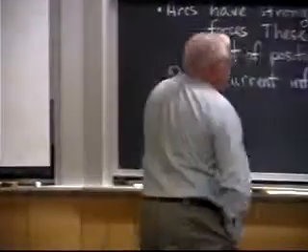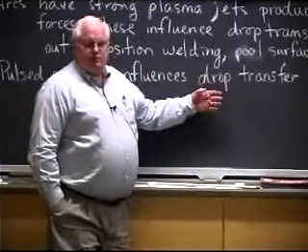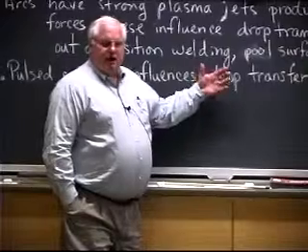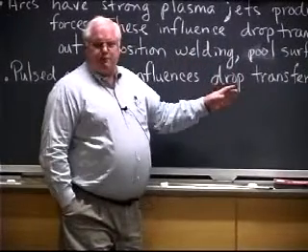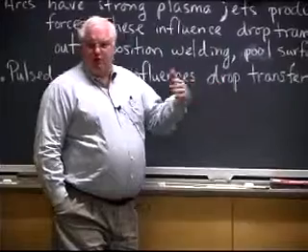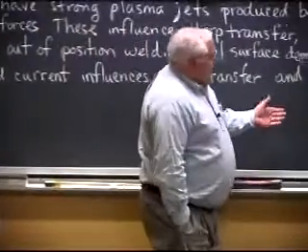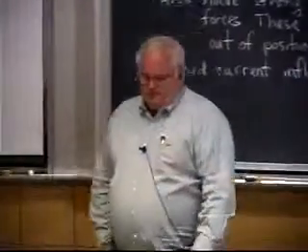If you coordinate it in around the 100 hertz type of frequency that these drops are coming off, if you drive it at 90 hertz or drive it at 140 hertz, you can actually get the drops to come off. If you try to drive it too far away from its natural frequency, then it won't respond. And it also increases the arc stiffness.